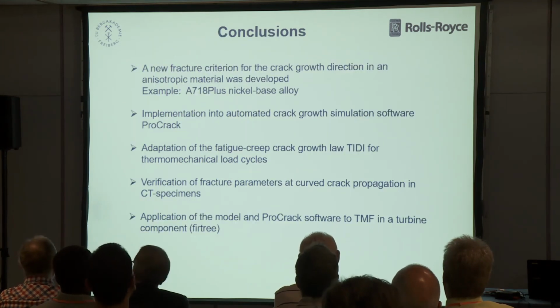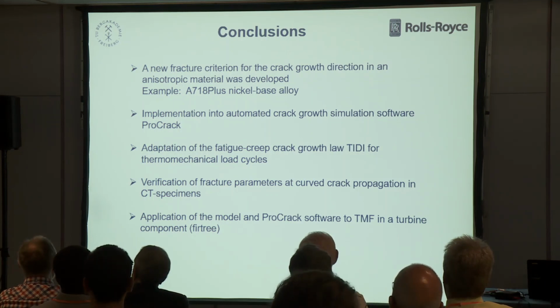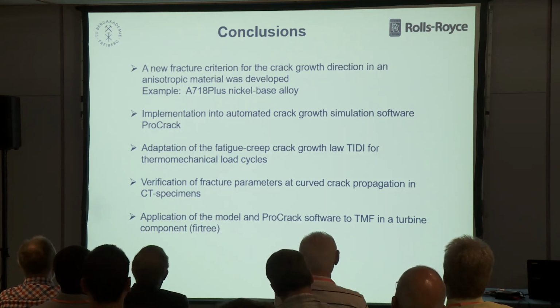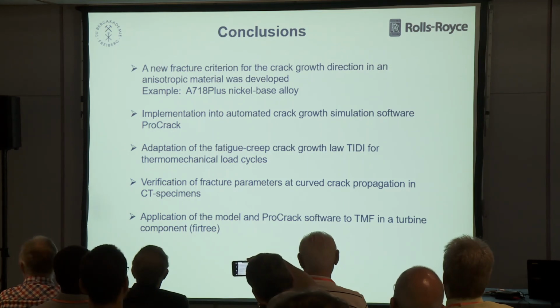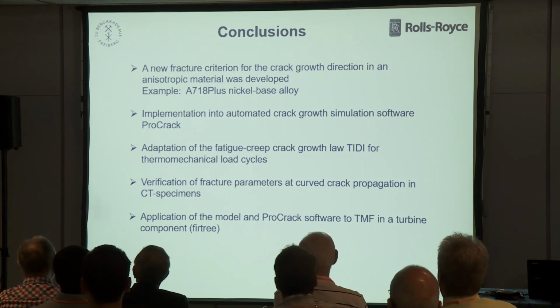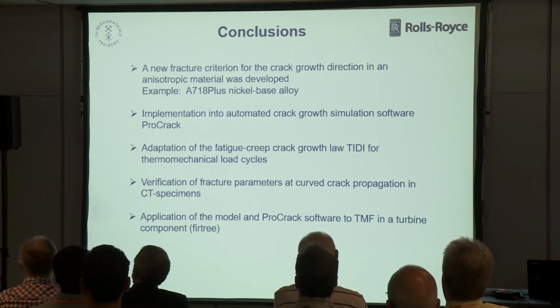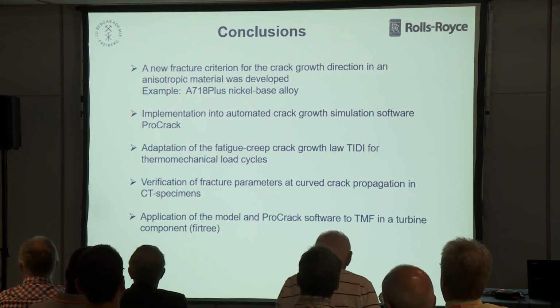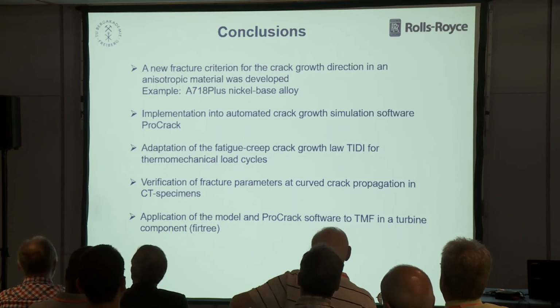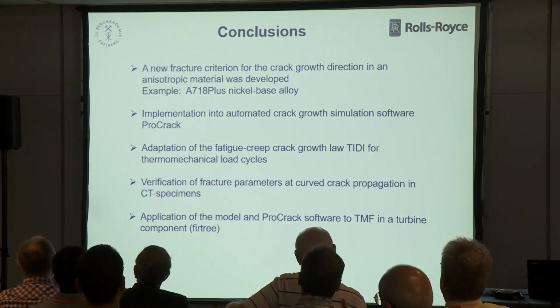Okay, these are the conclusions. So we developed a new fracture criterion for the crack growth direction in an anisotropic material. I think this is not only restricted to this nickel-based alloy. If you have another anisotropic material, composites, or what is now in additive manufacturing, we have also clear anisotropy in the direction parallel and perpendicular to the processing, or in rolled sheets. So we can use it.